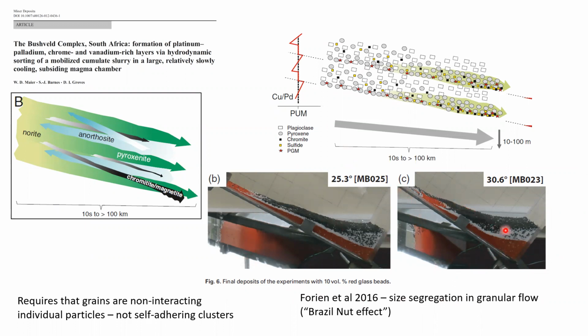What she showed is that you could mix up populations of beads of different sizes representing different phases, plagioclase, pyroxene, and chromite, and run these down a slope, a classic gravity flow. What happens is that the finer material, which in this case represents the chromite, segregates down to the bottom of the flow. This is sometimes called the Brazil nut effect. It's the same effect if you take a jar of mixed nuts, Brazil nuts, peanuts and hazelnuts, and shake it: the Brazil nuts rise to the top, because the smaller grains migrate down through the interstices between the larger ones. So this is the explanation which has been offered for forming chromite seams.